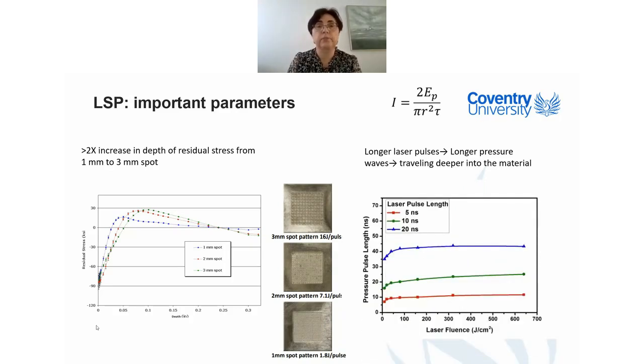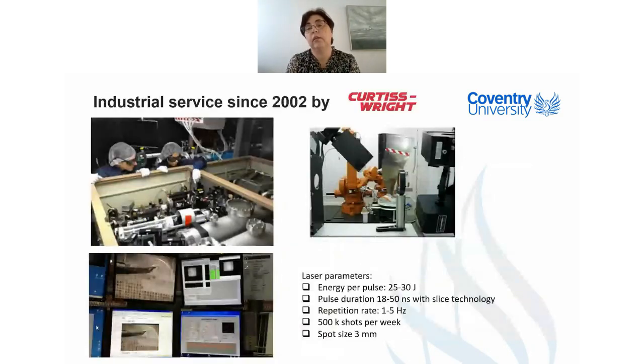Then if you look at just laser fluence, you will see that it depends on energy per pulse, pulse duration, and spot size. If we keep the same value but change just the spot size, you can see that we are already increasing the depth of residual stress 2 times if we go from 1 to 3 millimeters. But at the same time, you need to increase energy per pulse from 1.8 to 16 joules. Not only are you imprinting your residual stress deeper in the material, a larger spot size also increases the speed of the process. Another parameter I mentioned is pulse duration.